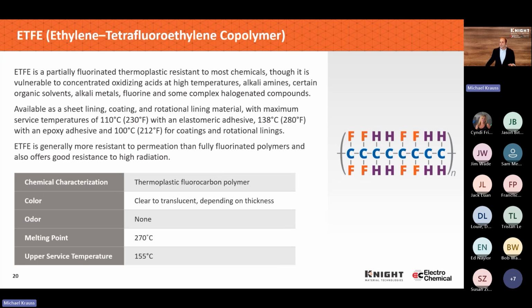Another material very similar to ECTFE and partially fluorinated is ETFE. When sold by Chemours DuPont, it's known as Tefzel. Looking on the right, you can see it's the long carbon backbone. Again, you've got the ethylene unit, the two with the 4 hydrogens, and then a TFE, a tetrafluoroethylene unit with the 4 fluorines. So similar. The difference between this material and Halar is that it has all 4 fluorines, where Halar ECTFE has 1 chlorine and 3 fluorines. From a chemical resistance perspective, it tends to perform very similarly to ECTFE.